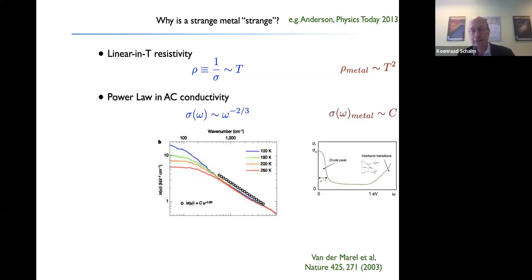Now, a second thing the strange metal shows is in the AC conductivity, so the conductivity, which is the inverse of the resistivity, but now not for a constant electric field, but for an oscillating electric field. It has a very characteristic power law in the mid-infrared around omega, and it scales there beautifully in a temperature independent way as omega to the -2/3. This is also very different from ordinary metals. In ordinary metals, there's a beautiful Drude peak, which dominates the transport at low frequencies, the DC limit in particular. And then there's a regime where you don't get a lot of conductivity. And once you have an electric field which is high enough that you can have interband or interatomic transitions, you again see that the absorption goes up.